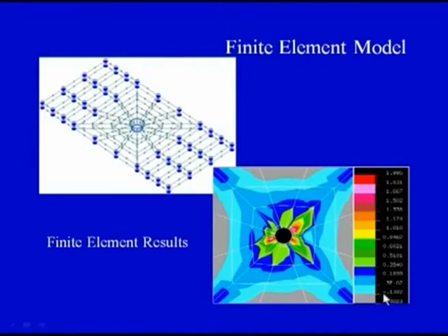Now on your screen you can see the output. One of the outputs is shown here. This red area indicates a failure plot, and the red portion indicates a value which is more than 1. It is precisely 1.995, and this pink portion is 1.831. So wherever these red and pink portions are, it means the damage has taken place at that place.